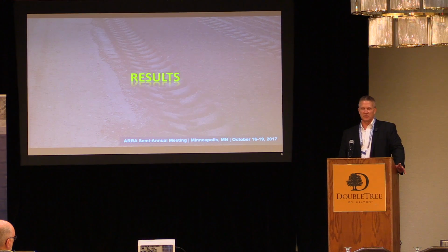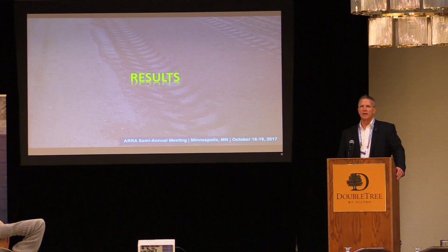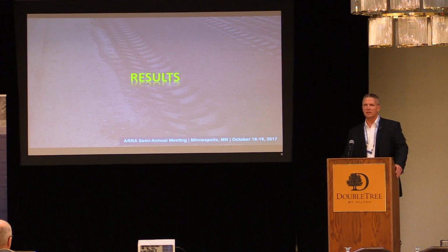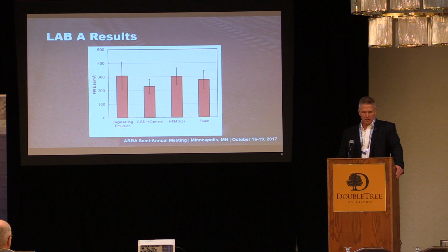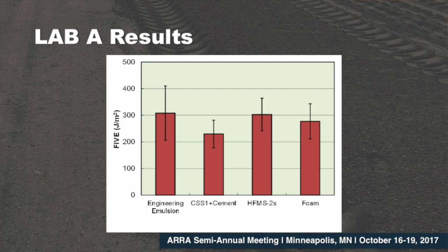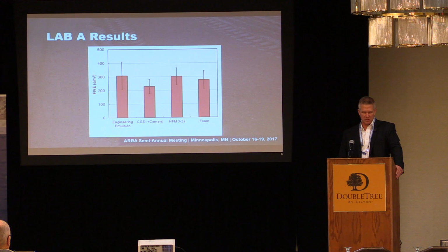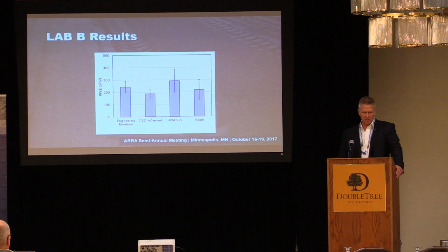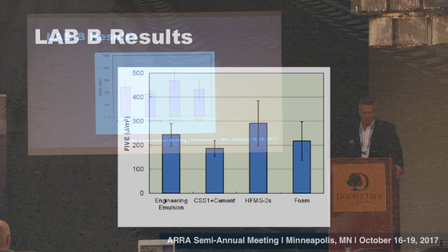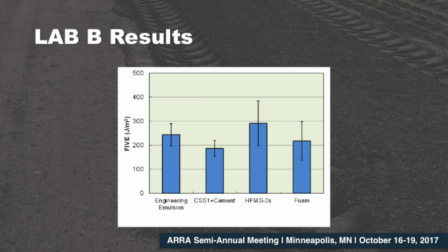But it's really important because the results, especially when you start translating from mixed design to quality control, quality assurance, are very important to carry any type of rehabilitation process forward in order to have reliability in distinguishing different types of not only binding materials, but the process itself in terms of providing the agencies with the results that they want. So you can see here, Lab A results had engineering emulsion, CSS1 with cement, the high float, and the foam. All had fracture energy values for the most part between that 200 and 300 area, where Lab B results, the only thing that was below the 200 value was the CSS1 with cement.